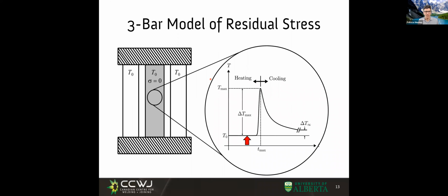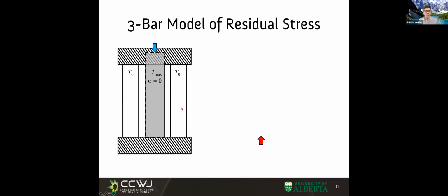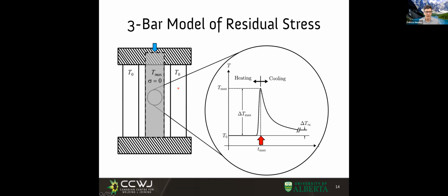So in this model, before we apply the load, before the middle bar sees temperature, everything is the same. When the bar starts seeing some temperature, it's going to want to stretch. But this stretch is not possible in this case because of the crossbar. In the case of a weld, it's not possible because it's the same plate and all the rest of the plate is cold. So the center cannot stretch. I cannot start squeezing out middle material, right? It's all tied together. So the middle material near the bead wants to stretch, but it cannot stretch.